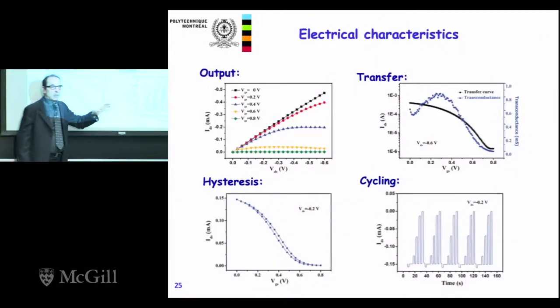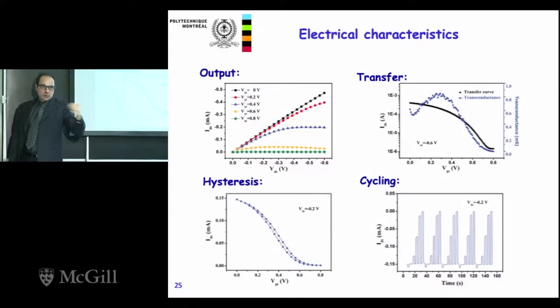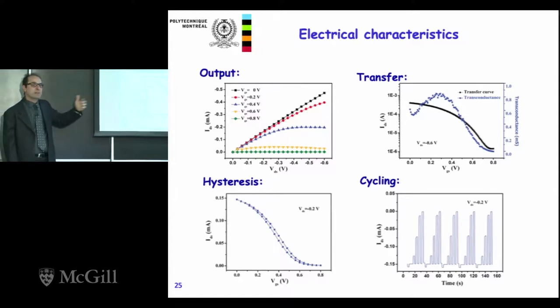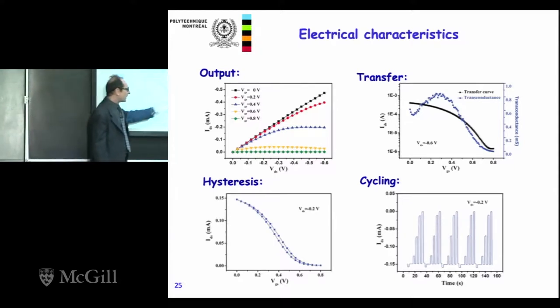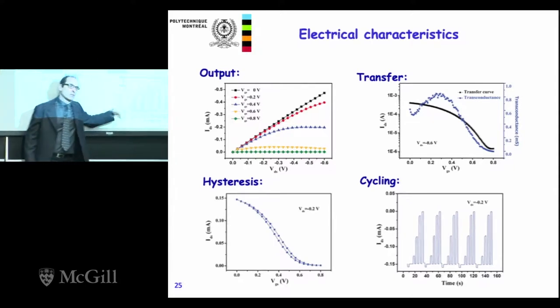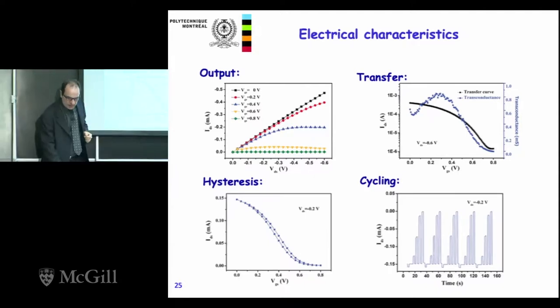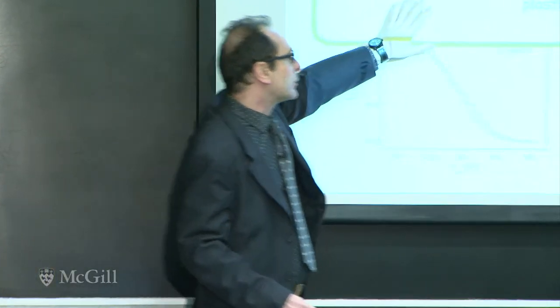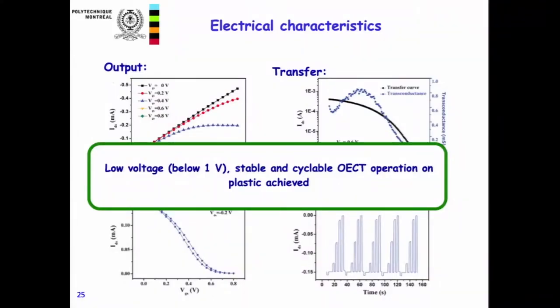And also other information is that you can cycle the device. This means that this doping dedoping process is to some extent reversible. Of course, after maybe hundreds or thousands of these cycles, we will get some irreversibility. But for a reasonable number of cycles, the stability is pretty good. And then, of course, the other message is that you can always work at very low voltage, so below 1 volt.